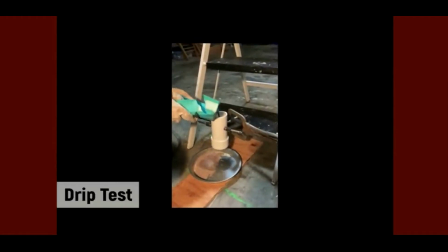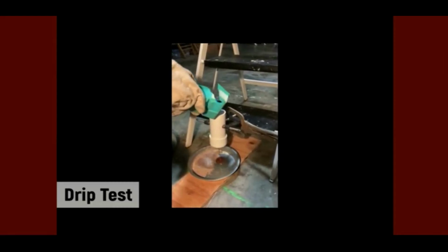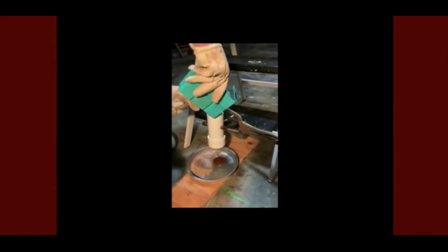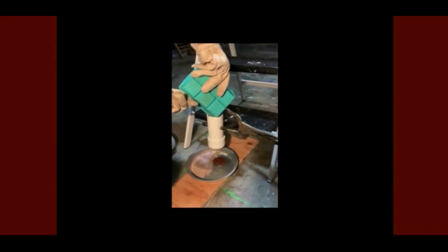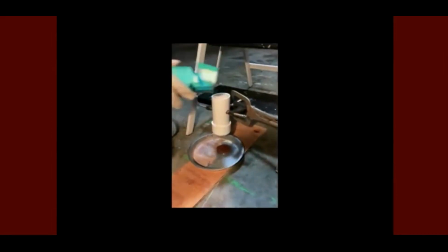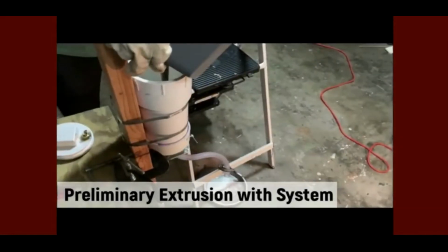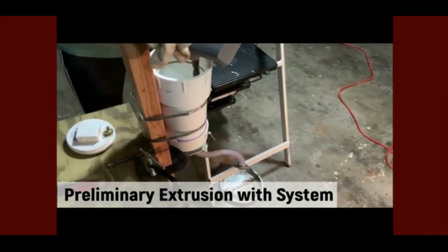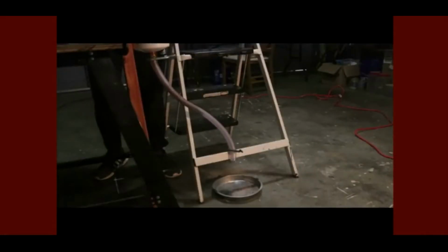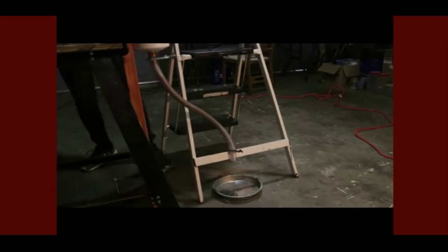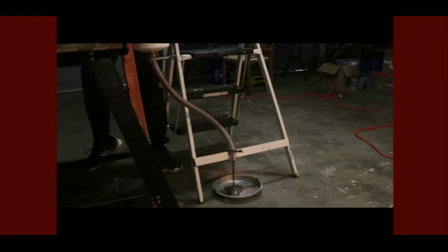So extrusion testing, I actually had to switch back to the less optimal 50-50 ratio because the thicker 55-45 kept solidifying in the tubing and just getting clogged. So I ended up fixing that by using some hot water run through to help heat up the tubing. And additionally, I ended up powering it with gravity. I had also tried air compression and a manual plunger, but gravity at a steep angle was really the only thing that could get it flowing fast enough so it wouldn't be solidified.